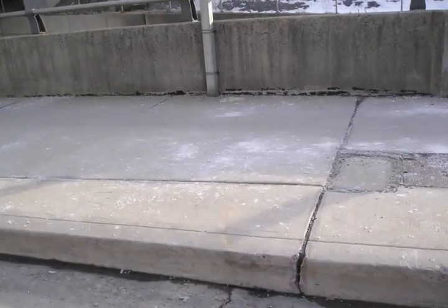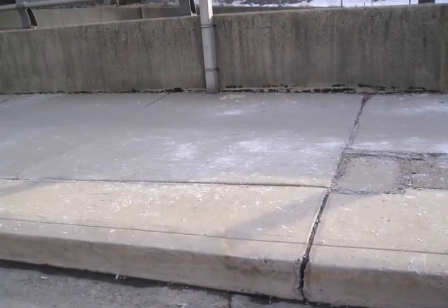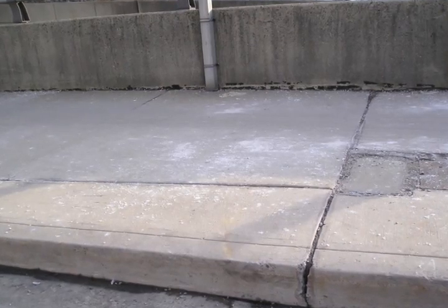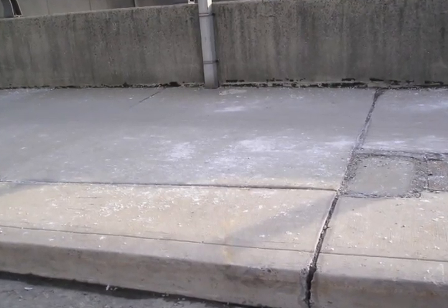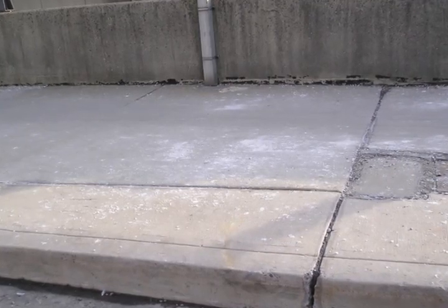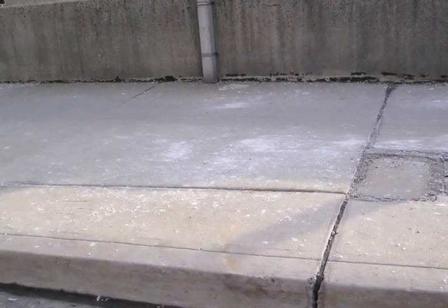To combat the otherwise slippery condition, departments of transportation routinely apply de-icing salts on our highway bridges and roadways to reduce the effect of icing. Here's a picture of the salt that's accumulated on a bridge in New York. And to give you some idea about our application rates in Utah, we apply about 250 pounds of salt per lane mile with each de-icing event. So to put this in perspective, to treat the entire length of University Avenue here in Provo and Orem, we would need 15,000 pounds of de-icing salt with each event.